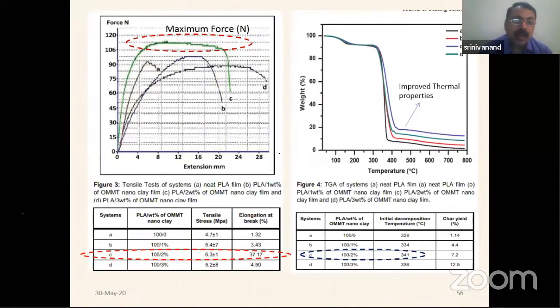We also did the mechanical stress-strain curve. As you can see, the green one indicates PLA 100% and then 2% of montmorillonite. When we reinforce only 2% of organically modified montmorillonite, we were able to observe a phenomenal improvement in mechanical properties. It is the same with thermal properties, which are improved for the 2% OMMT clay-loaded PLA nanocomposite materials.